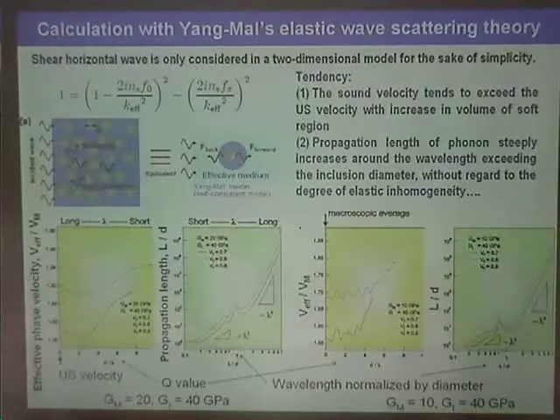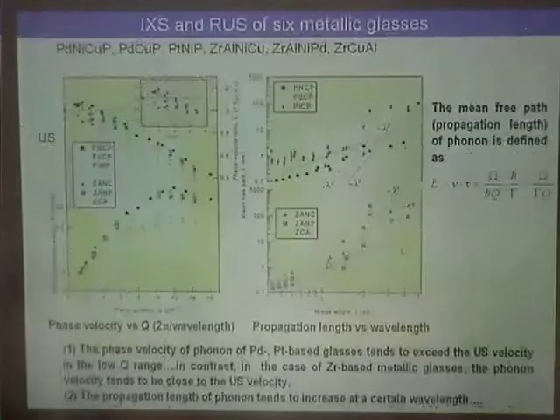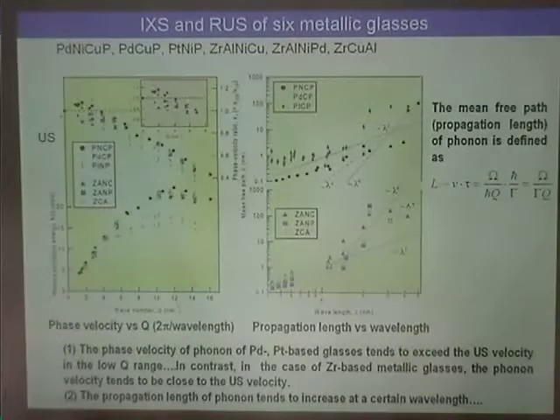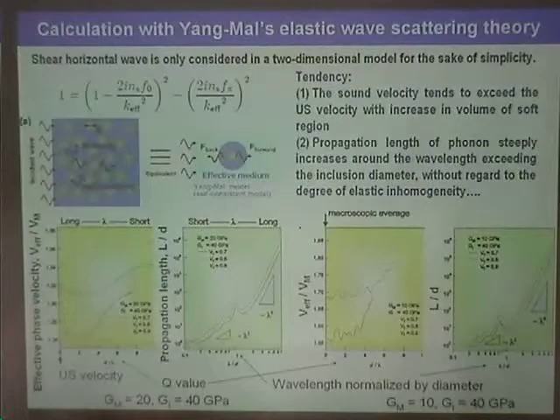Sorry, would you mind just going back to the previous slide? Would you then say that previously you argued that the phase velocity extrapolating to above the ultrasound limit is evidence for a length scale? But in the zirconium-based metallic glasses, where you never get above that velocity, there is no such length scale and the structure is more homogeneous? Yes, I like to say more homogeneous. And palladium glasses are known to be two-phase segregated. This is microphase segregated? Okay.